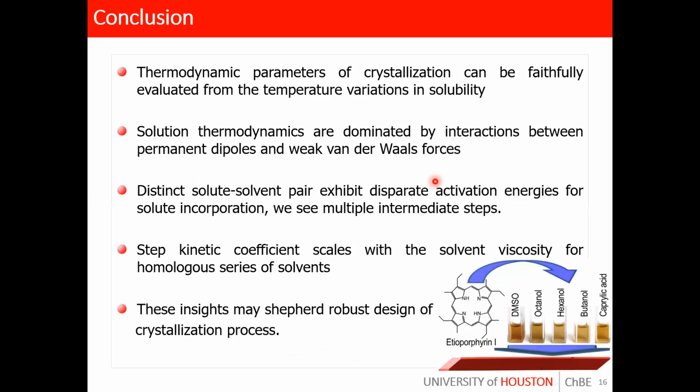So overall, I would like to conclude by saying that thermodynamic parameters of crystallization can be faithfully evaluated from the temperature variations in solubility. We have also shown that in this particular case of solute-solvent, the solution thermodynamic parameters were mostly dominated by interactions between permanent dipoles and van der Waals forces. These are weak forces of interaction, because of which the solvent structuring at the crystal interface is negligible.